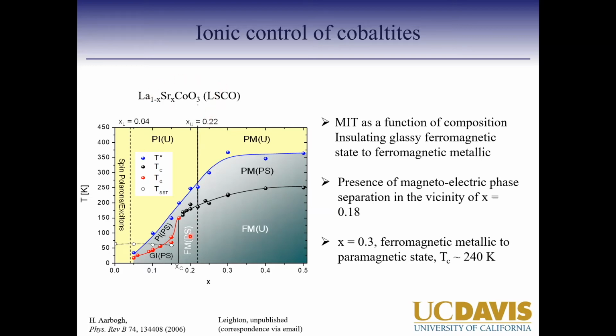They made it for different compositions, and this material is interesting because as a function of composition, it shows a metal to insulator transition. For the lower compositions of strontium, it's insulating. It acts like a spin glass, where you have certain ferromagnetic regions in an insulating matrix. As you dope more and more, these ferromagnetic islands grow and the material becomes completely ferromagnetic, and those ferromagnetic channels are magnetic and metallic, so the material becomes metallic. At around 0.18 composition, you get to this metallic ferromagnetic phase. So that's where we were. We used a composition of 0.3, where the system was deep in this metallic ferromagnetic phase.